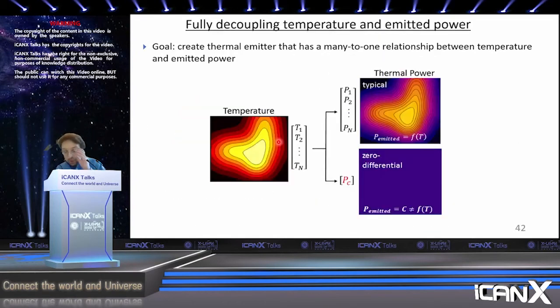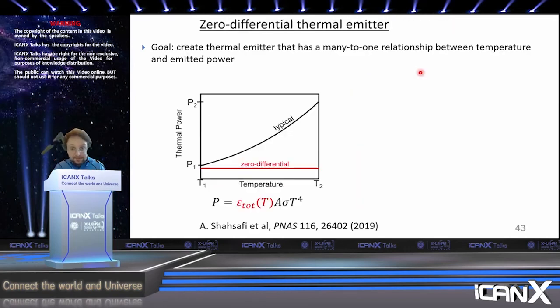So, okay, now that we can have a region of negative differential thermal emittance, we had this goal when I was starting out at UW-Madison to create a thermal emitter that has a many-to-one relationship between temperature and thermally emitted power. Essentially, instead of each temperature mapping to a different power, here I want each temperature over some temperature range to all map to the same power. In other words, have a zero differential thermal emitter, because I think this would be very interesting for concealing information that's provided in thermal radiation, for infrared privacy applications.